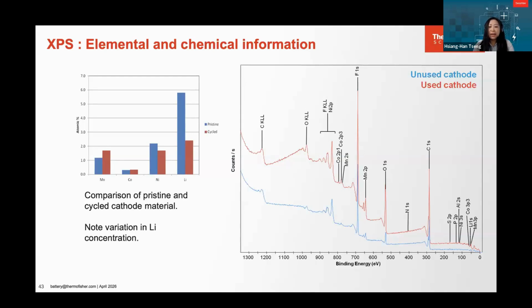On the right-hand side, there are survey spectra collected from the as-received cathode samples. The cathode material is based on lithium, nickel, manganese, cobalt oxides, prepared using a binder medium to hold the material together. The binder itself is based on a mixture consisting of a fluorine and carbon polymer. And you see that for the pristine sample, it's quite evident that there's a significant residual amount from the electrolyte and from the binder.